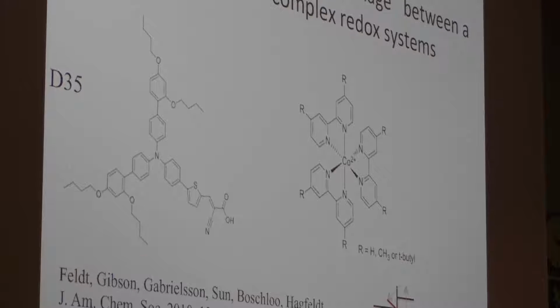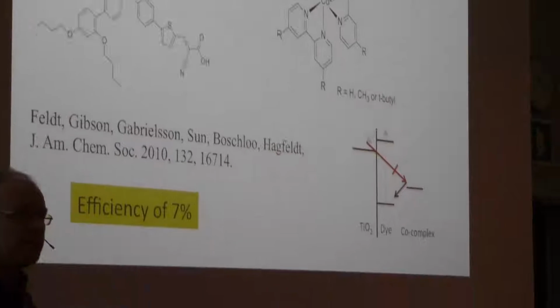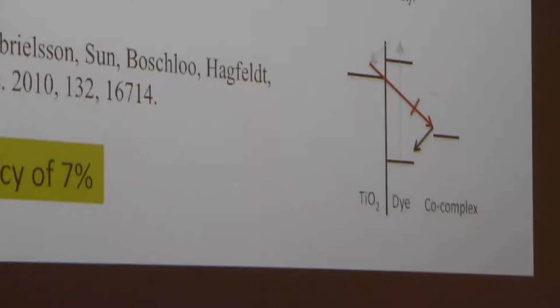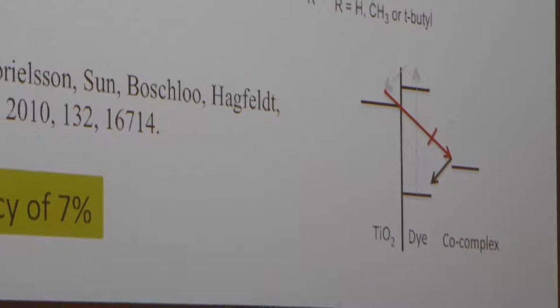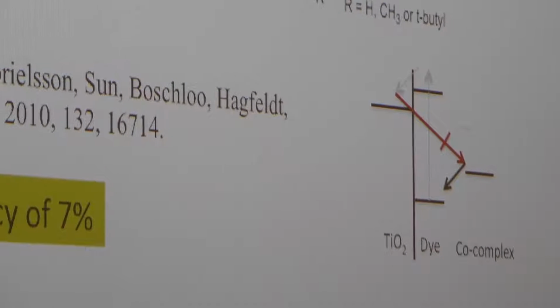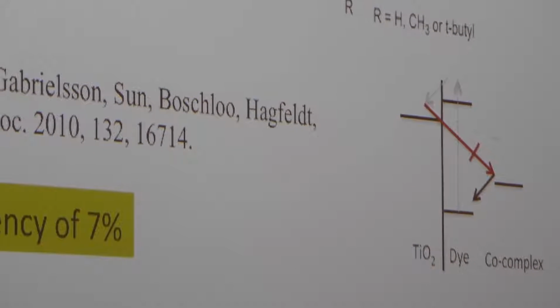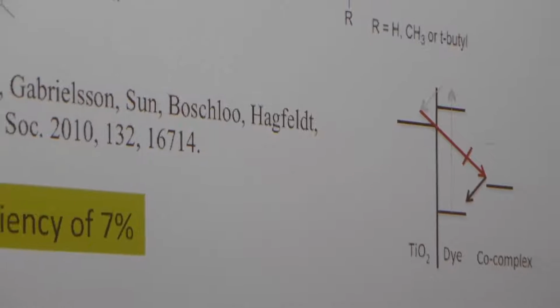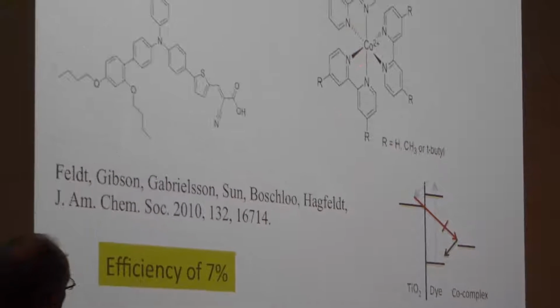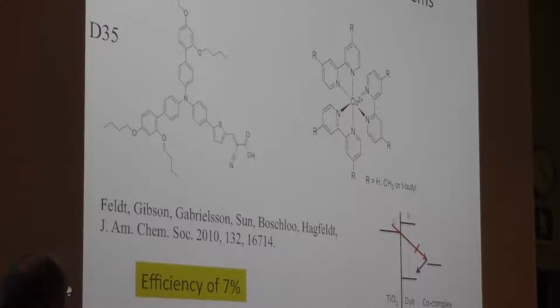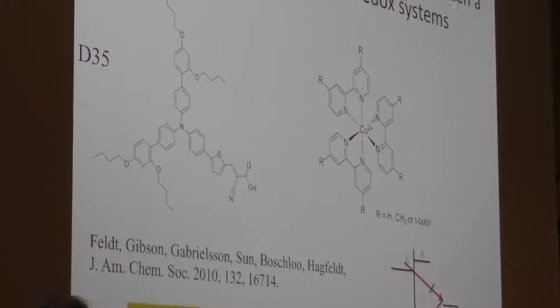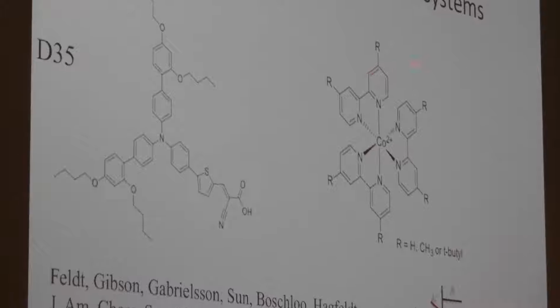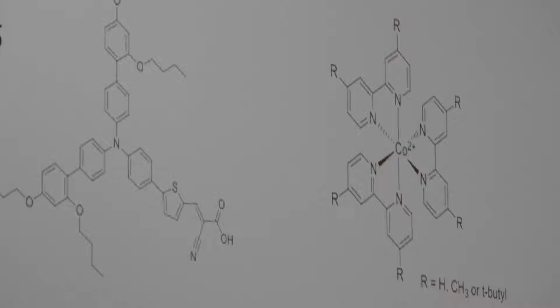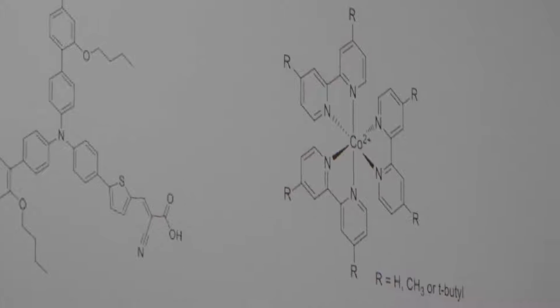What happened with this dye was that it passivated this recombination reaction. So this reaction of electrons to the electrolyte was 100 times slower with this dye than we had ever seen before. So that means that the dye itself can passivate the surface. And then we were thinking, now maybe we have a chance to change the redox system. And our first choice came from work on nickel oxide as a P-type photocathode dye sensitized system. And it was to use this cobalt tris(bipyridine) complex as our new electrolyte. So it was really a combination of things.